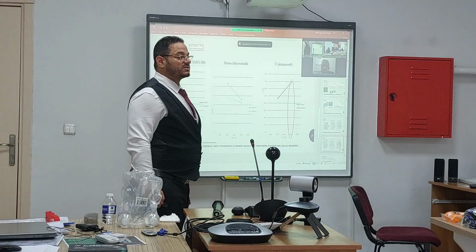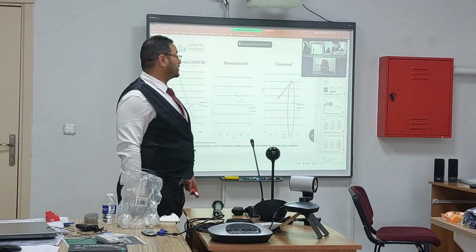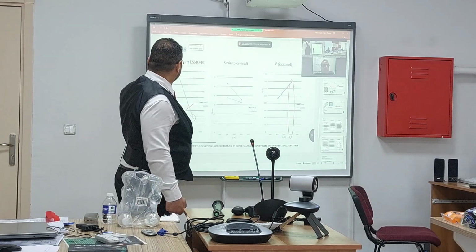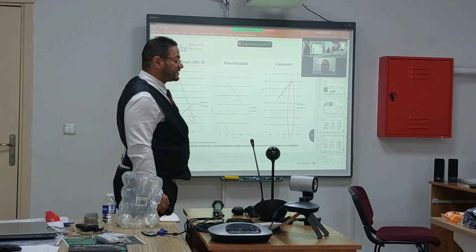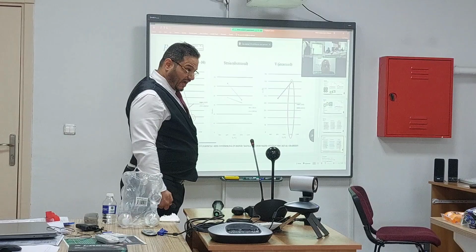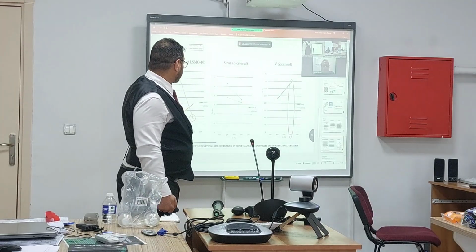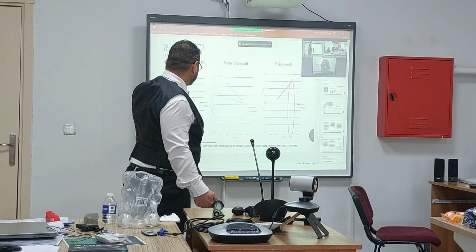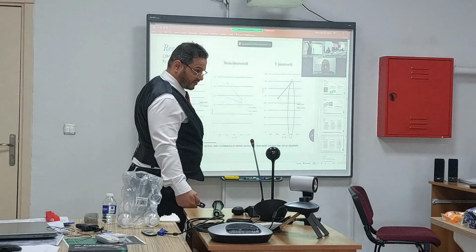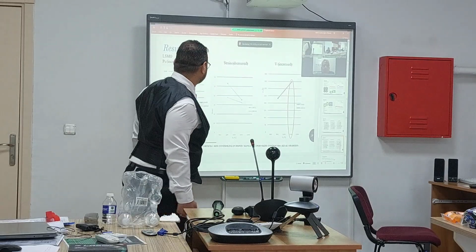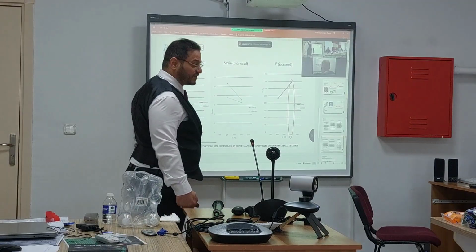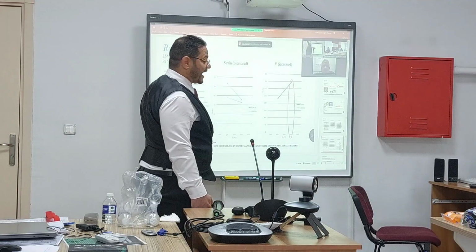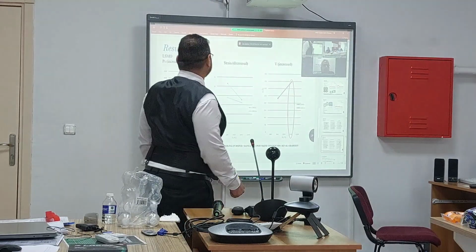Here now I'm talking about lanthanum strontium manganese oxide. Here I have something unexpected, because the particle size at 900 was more than at 1100. But at 5 molar ratio, it acts normally, it increased when you increase the temperature from 900 to 1100. Here, it's somewhat different from calcium doping. The volume, like I expected, all of these increased.